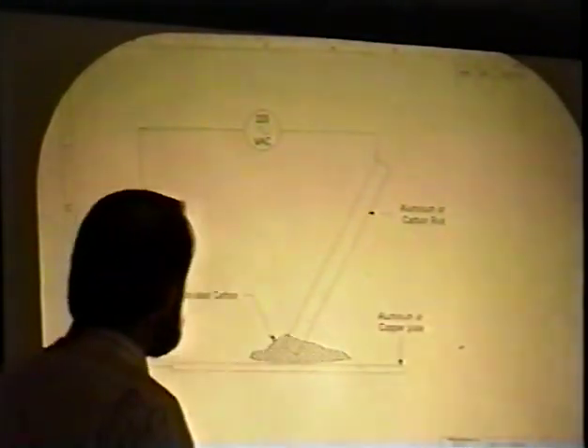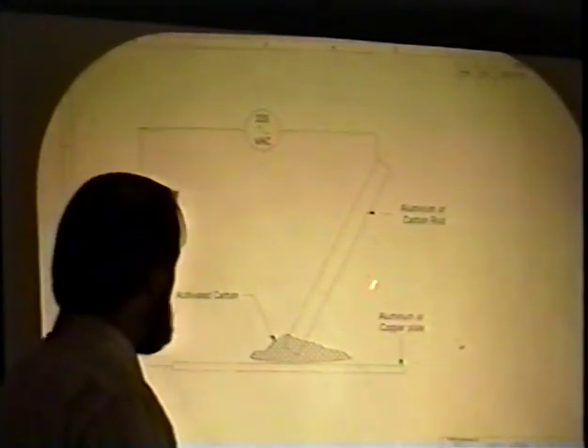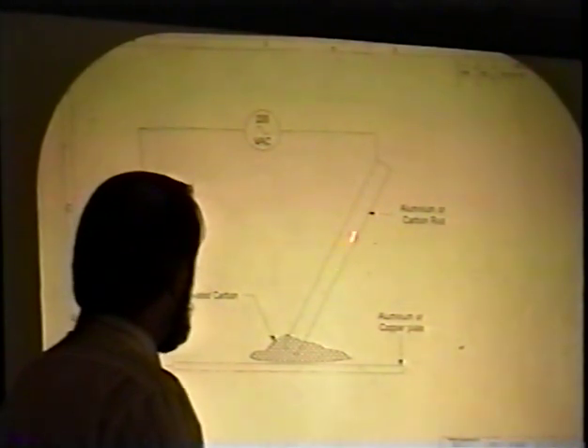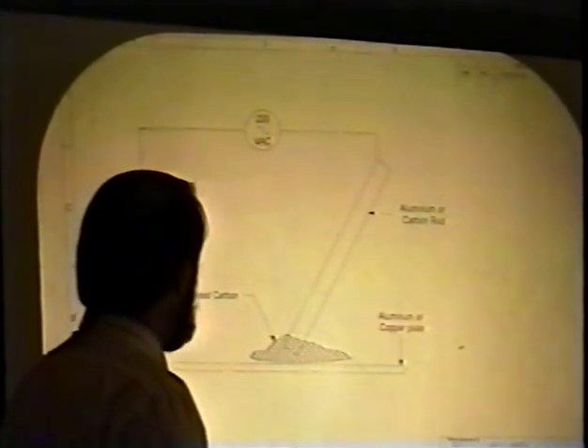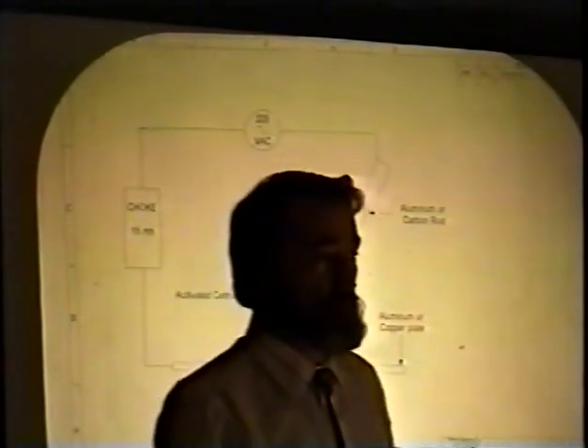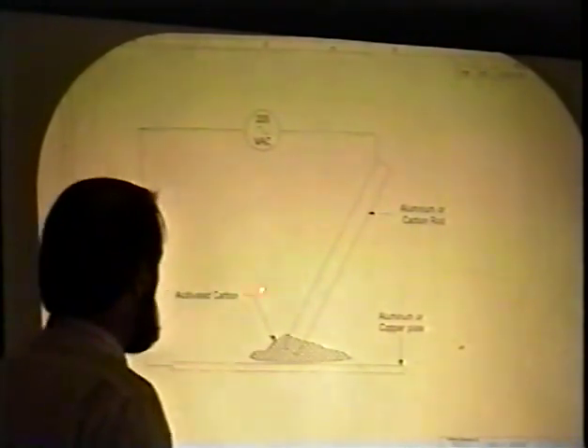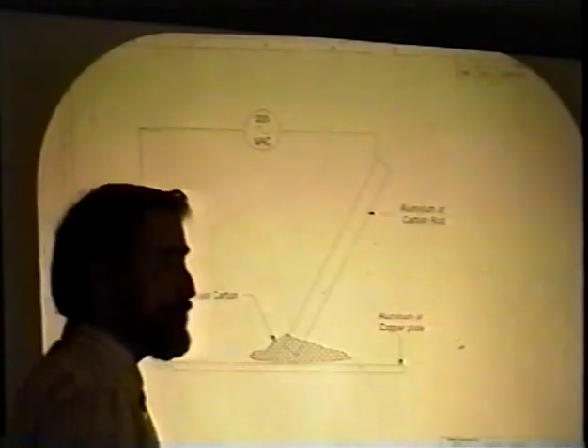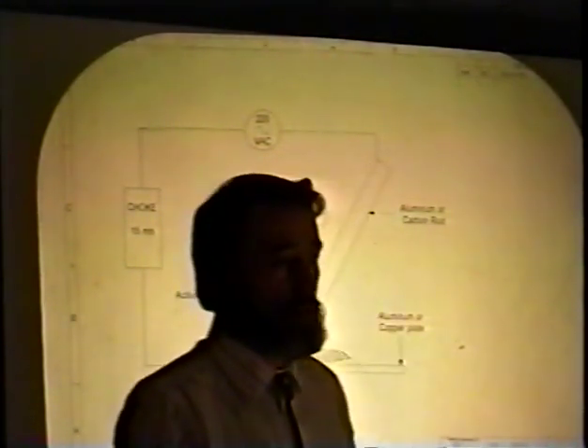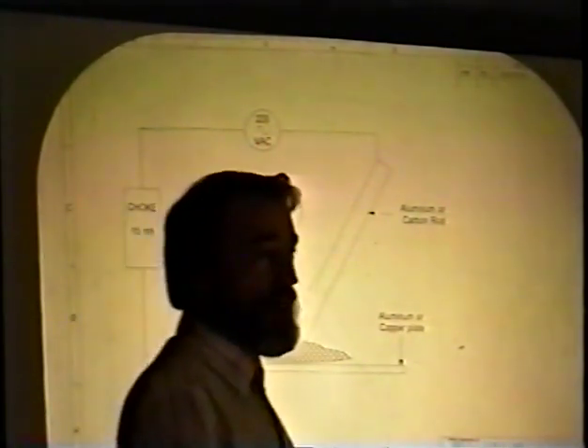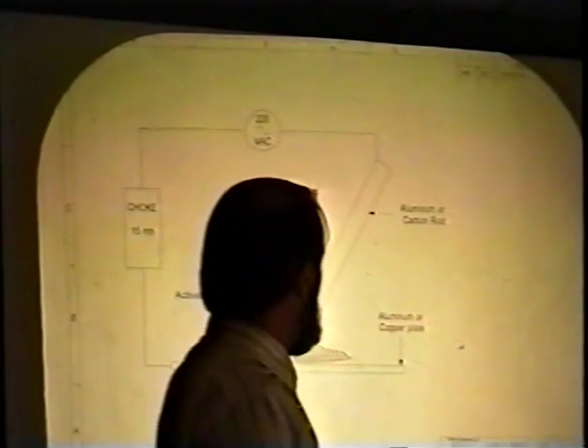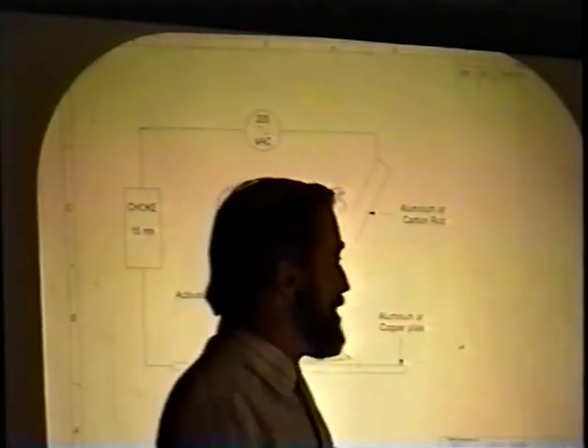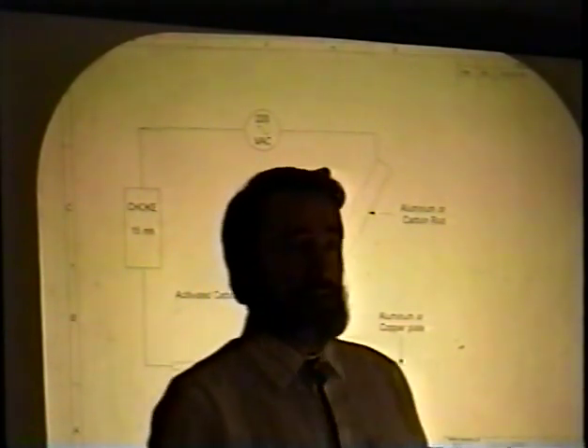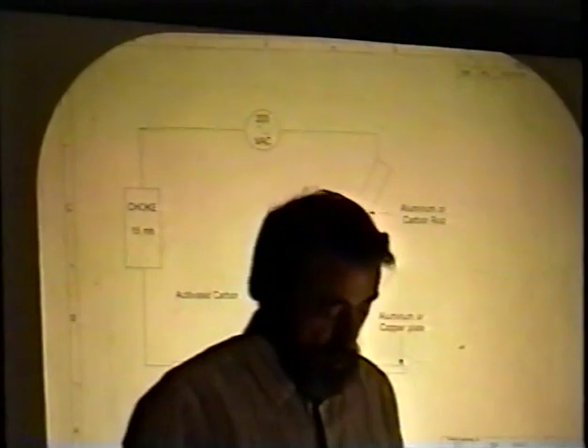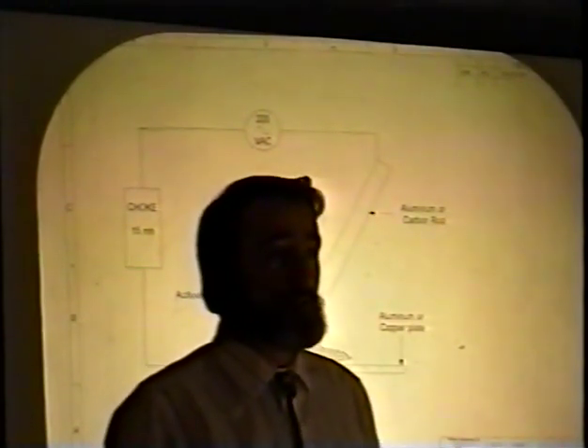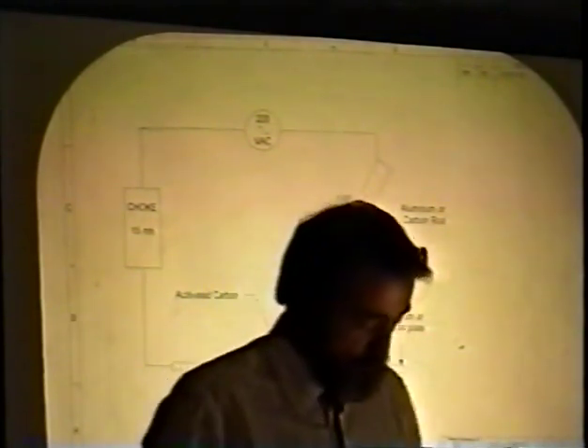We also, because we'd seen this particular experiment described with a copper plate and a carbon rod, tried an aluminum rod and aluminum plate of 6061-T6 material in order to eliminate the possibility that there was some type of interaction between a carbon rod and a copper plate. We did find the same results whether we used an aluminum rod and aluminum plate or a carbon rod and a copper plate. So that led us to the conclusion there really is no dependence on the materials you're using for a base plate and what you're using to stir the material with, and we're assuming that the effect that occurs is basically due to the carbon arc, the spark discharge.